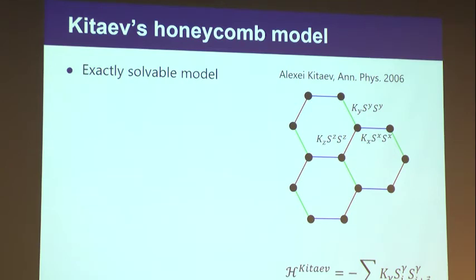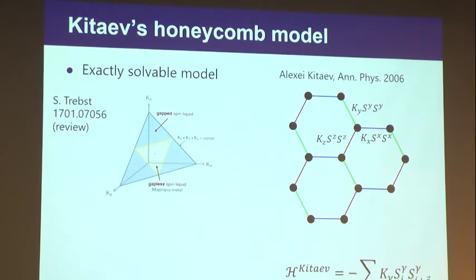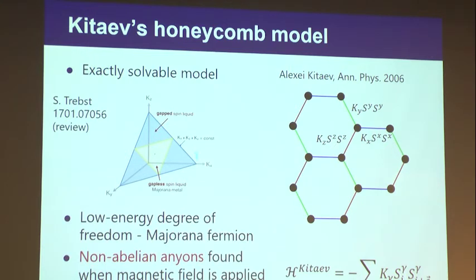Not only did he propose this model, but he solved it, and he showed that you can solve it exactly, which is extremely rare in physics models. More importantly, he found that there are a bunch of different quantum spin liquid phases in this model. Depending on the strength of the x, y, z direction interactions, you can have a gapped spin liquid or a so-called gapless spin liquid. In the gapless spin liquid, the low energy degree of freedom is the Majorana fermion. But what's really important is that in this particular gapless phase, if you apply a magnetic field, you will find non-abelian anyons.